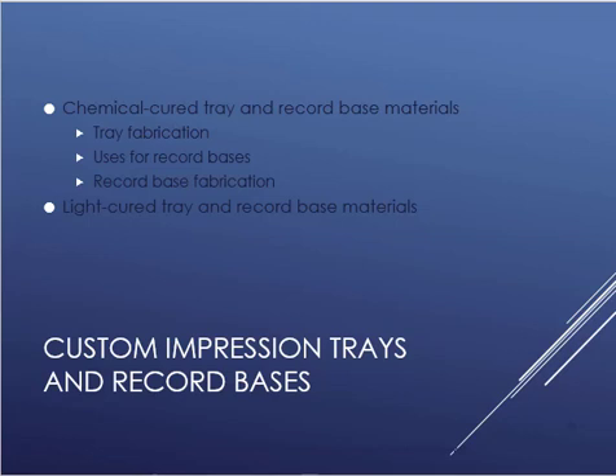Similar to other chemical cured acrylics, the tray materials are supplied as both a powder and a liquid that are mixed together. And when that mixture reaches dough stage, the material is adapted over the tissue portion of the cast by hand and to a uniform thickness, so an even thickness.